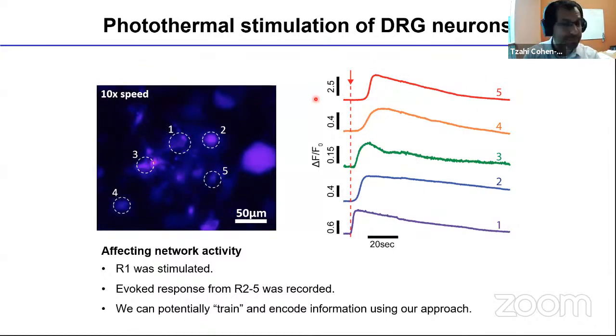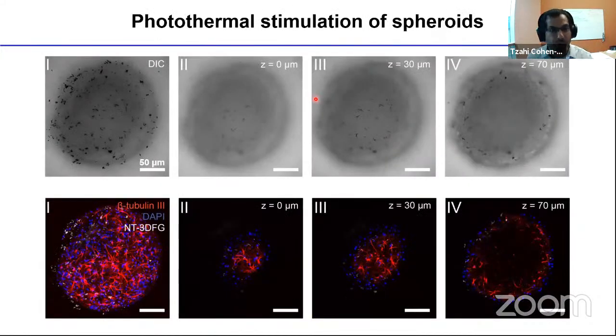Something really unique about this approach is that we are not limited to two dimensions. We are not limited to a single cell. One can sprinkle it on organoids or spheroids. One can mix it in with a certain threshold below the toxicity. As we all know, we need to test it, and we've done it. In this case, you can see NT3DFG mixed in cortical spheroids, and you can see that the particles are dispersed all over the spheroid. This one is literally sprinkled, like a cupcake. We sprinkled it on top, but we have other data showing that we can mix it in as well.